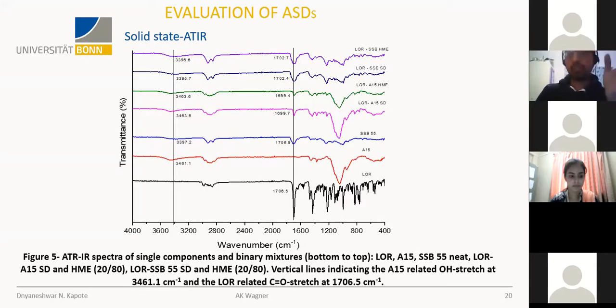Then we did ATR-IR in order to investigate the molecular interaction. Loratadine is a weak base, showing a C=O stretch at 1706, while Affinisol has higher OH groups, observed at 3461.1 cm⁻¹. In shellac, we observed that the C=O group was there and also the OH group. So the C=O group was observed at 1706.